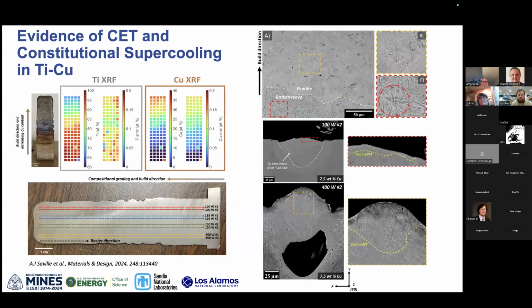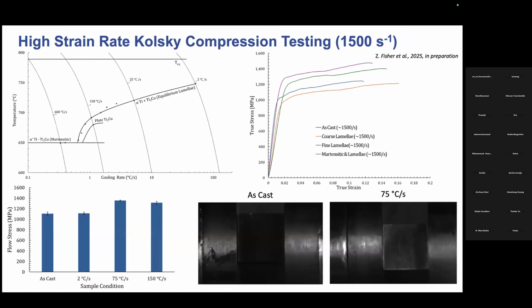We did a little bit of work after that where we did some DED builds in collaboration with Sandia National Lab, where we compositionally graded up the build height. We then laid laser track melts in that and looked at the microstructure. And we tend to see around the eutectoid composition that we actually have CET. So we believe that we have both of these things happening, and it's more prominent at the eutectoid composition. But again, this is a unique kind of system, maybe especially suited for additive manufacturing.